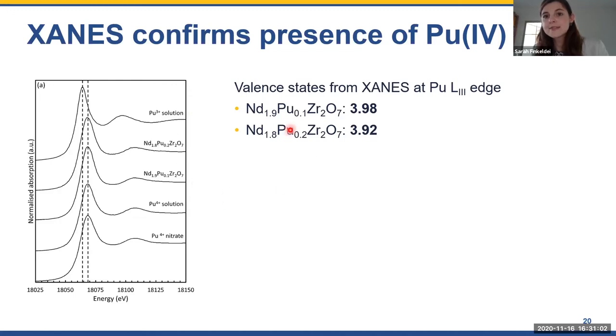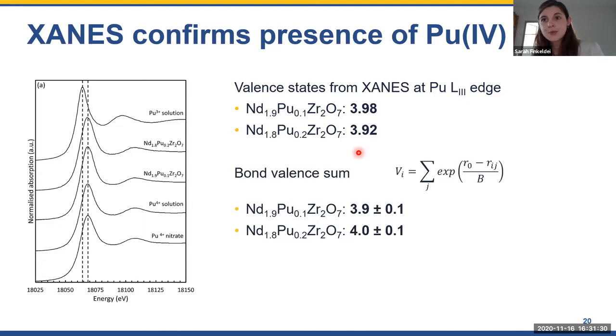So the valence states from the XANES measurements at the plutonium L3 edge showed us that in both cases, so 5 and 10 mole percent plutonium loading of a pyrochlore waste form, we obtained plutonium in the oxidation state +4, which is a little surprising considering the fact that we were performing all sintering processes and calcination processes in reducing atmospheres. So to be more confident in those derived data, I performed bond valence sum calculations from the EXAFS data, and those also obtained values of +4 for plutonium in both of the ceramics that I had fabricated.